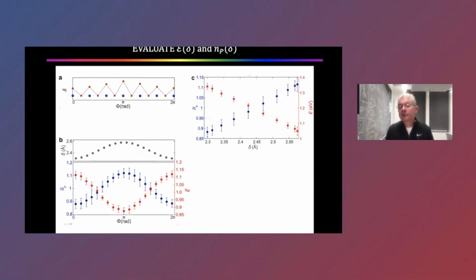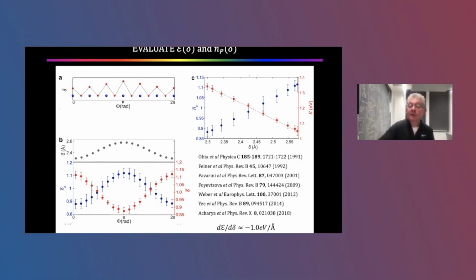If you do that, then you can plot number density of pairs versus apical distance, and it shoots up. The bigger the apical distance, the stronger the superconductor. Haha, people predicted that 35 years ago. Charge transfer energy, it shoots down. And in fact, it shoots down on the curve which has been expected for more than 30 years. It does exactly what's expected.